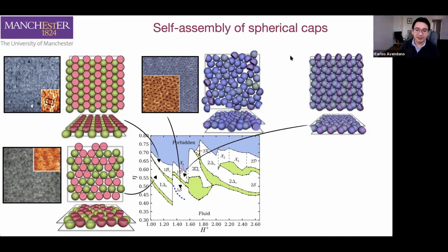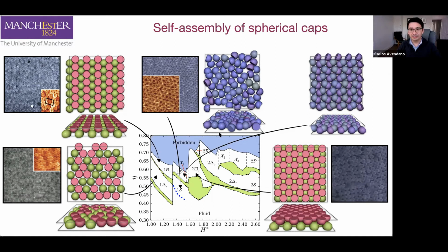And once that we increase even more the distance between the two walls, so we decrease the degree of confinement, we start observing the first formation of layers that again is similar to what you will observe with spherical particles. And this is again in complete agreement with the experimental observations by Chekesha Liddell. So far we are observing that indeed the experimental structures are in thermodynamic equilibrium as proved by the computer simulations.